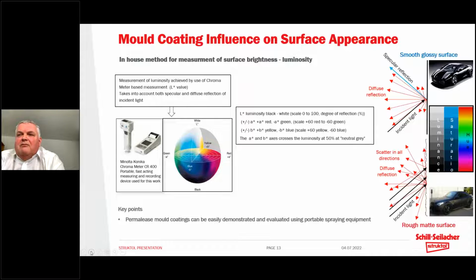And if we contrast that to some of the matte surfaces that we see on cars that are also becoming popular now, this is achieved by applying a foil onto the surface of the car. And this foil is a very irregular surface. The colour is the same. You can have black, and the black is the same, but it looks now very matte because the light is directly interrupted and reflects in a non-uniform manner, and we simply see that as a very low shine. So if we could apply the same behaviour to the surface of the mould, perhaps we could also produce shiny or matte surfaces of the rubber articles in contact with that mould. So this is something additional to the quality of the surface of the mould, to directly change the aesthetics of the moulding just by altering the surface appearance on that moulding. Next, please.